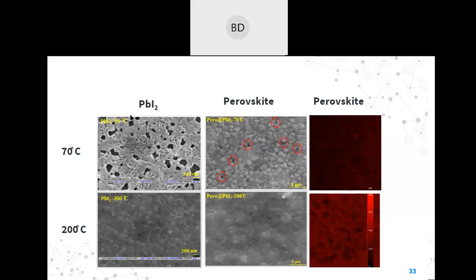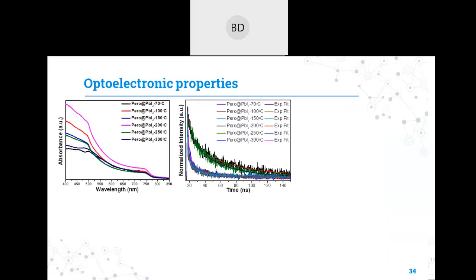And if you convert this PbI2 into perovskite, this is the difference here. This perovskite is showing a very compact morphology, and it's very hard to see the grain boundaries even in this morphology using the SEM. If you see the luminescence in both the perovskite films, the perovskite which is formed by annealing the PbI2 at 200 degrees centigrade gives a very good photoluminescence as compared to the perovskite which is made using PbI2 at 70 degrees centigrade. Not only the morphological properties, the optoelectronic properties of the perovskite have been improved significantly.